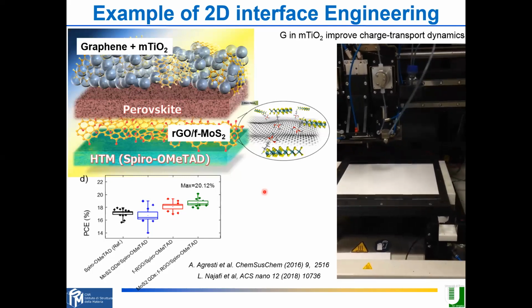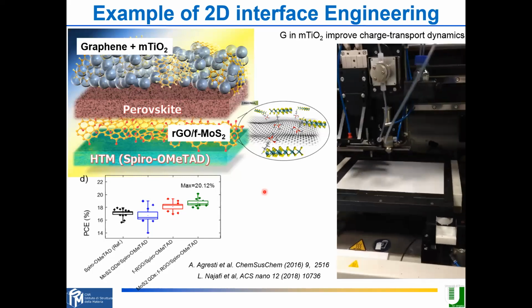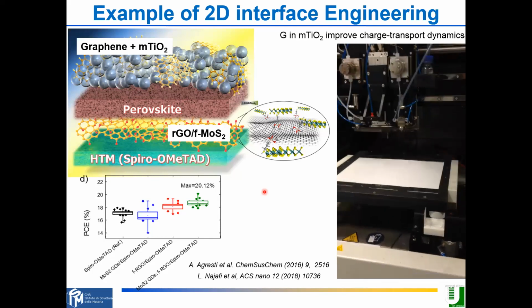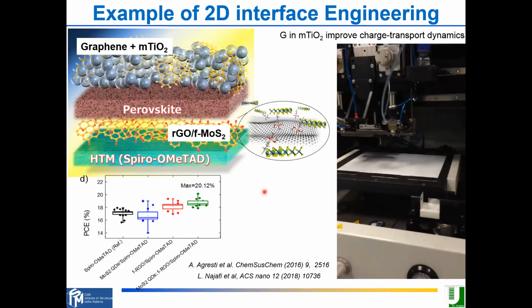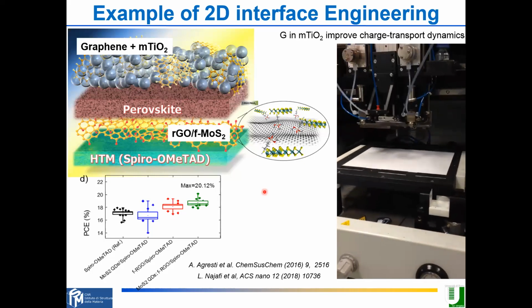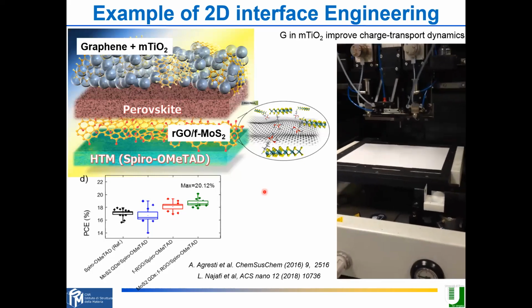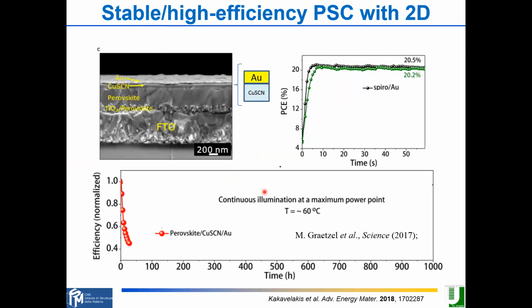The use of 2D materials also has a strong impact on the stability of the solar cell. I would like to show something which is not the result of our group, but the results of Michael Grätzel. This is a sketch of a solar cell where you have a gold and copper thiocyanate interface, and then the rest of the solar cell is a copper thiocyanate hole transporting layer.